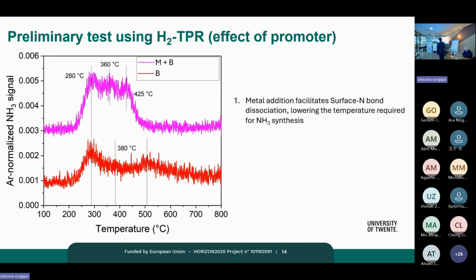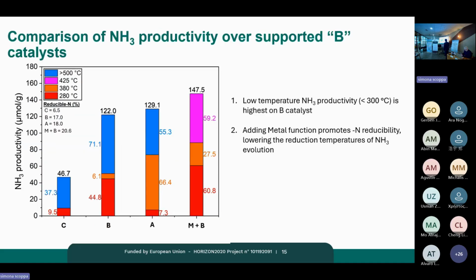And the temperatures also shift towards slightly lower values. We have actually newer materials that I'm not showing you today that show an even much larger concentration of ammonia evolution. Now you can take that data, and what you see here, generally speaking, is that you have three different types of temperatures, and you see the region we're interested in is the temperatures that go all the way to maybe 300 degrees C at most. And so we're interested in this plot over here, and you see that now we have a formulation that is very promising for such an operation window. At 280 degrees C and about maybe 50 bars of pressure is the idea that we have for this.